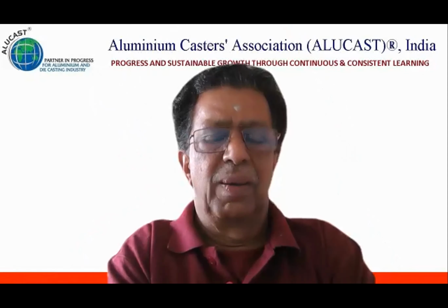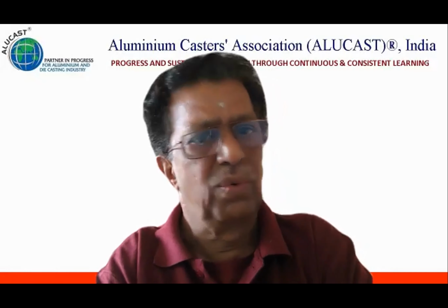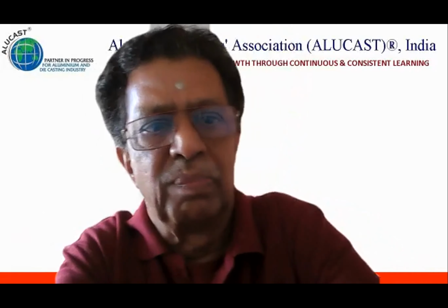There is a question from Mr. Dhananjay again. Wire mesh and ceramic mesh, which is better for low pressure die casting? Well, if you are doing sand casting or a bigger casting by sand, I would go for a ceramic filtration, where the filtering efficiency is extremely good. If you are using a wire mesh, the problem is that on remelting the runner and riser, the wire mesh is bound to come into the molten metal, and the iron pickup will drastically go up.